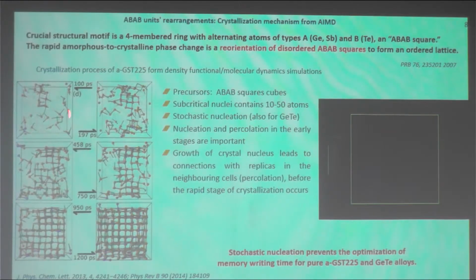So in this model, in the crystallization process, we start from the amorphous state consisting of these AB squares, and they are considered as a precursor in this system, like a nucleus. However, it requires at least 10 to 50 atoms to form such a nucleus. The nucleation process is a statistical process. It requires some time. So there is nucleation and percolation in the early stage, and the system can form a nucleus and then go back. But if a stable nucleus has been formed, then the system can start to crystallize, on picosecond scales